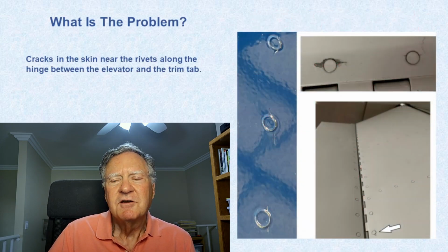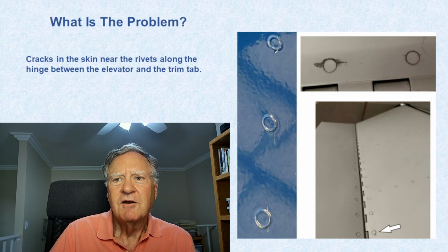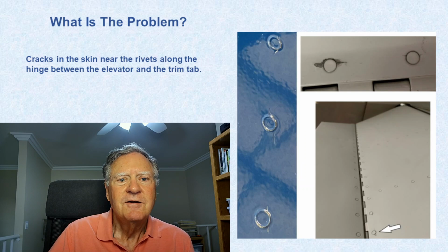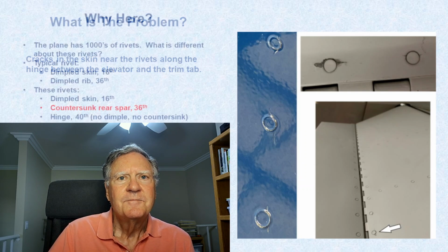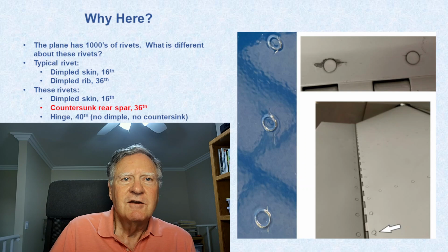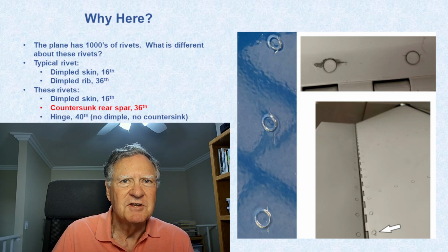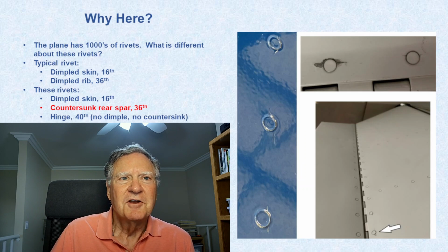Okay, as I already mentioned, the problem is in the elevators along the hinge to the elevator trim tabs. And you can see that hinge in the lower right photo. The cracks are clearly originating at the rivets along that hinge, as you can see in the upper right photo. Okay, so an RV10 has thousands of rivets. So what's different about these rivets? Why do they have cracks and all the rest of them don't?